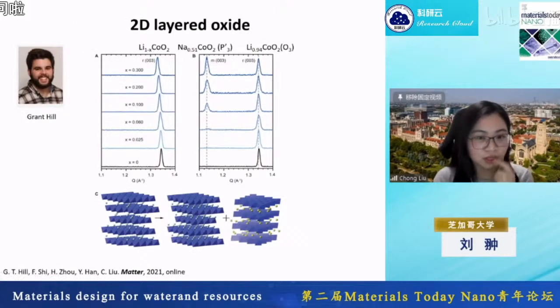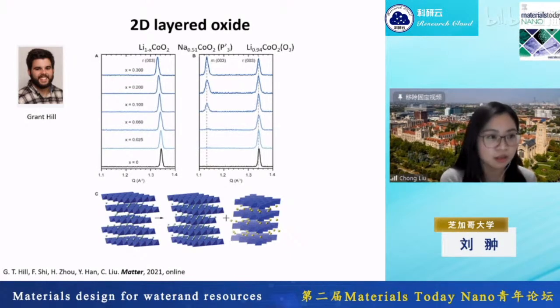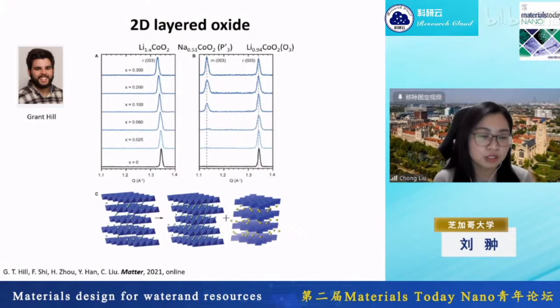And this is our newest work, and we do observe the strong sodium interaction with the lithium, in that whenever you create a vacancy in the host layered oxide structure and you put it into a sodium-rich solution, there will be automatic ion exchange happening. And the ion exchange happens in a way that is not a simple sodium ion replacing the lithium ion in its original place, but a forced phase separation, in that when sodium comes in, it squeezes all the lithium ions into a corner so that it forms a phase without any vacancy. And all the vacancies are given to the sodium phase, so they have a phase separation.